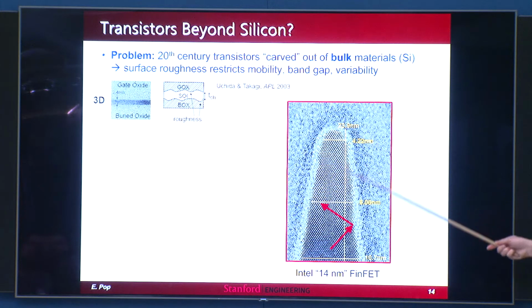This is a cross-section of the so-called 14 nanometer FinFET technology from Intel, which is inside my laptop right now. I say so-called, and I put it in quotes, because notice there's no 14 nanometer dimension in there. 14 nanometer doesn't really mean anything. It just means it's somehow better than 22 nanometers, just like my Google Pixel 2 phone is better than the Google Pixel 1 or something like that. But it is small. It's impressively small, and you can see every atom in here, which just blows my mind. I think this is very, very cool.